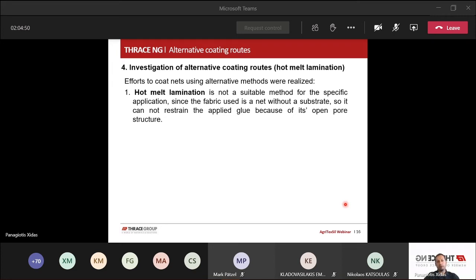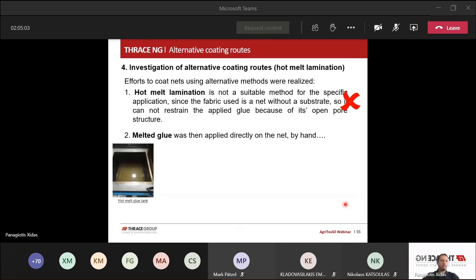So since the use of the lamination machine was not feasible, we tried to apply the glue by hand, very simply, with the aid of a brush. Here in the image, you can see the tank of the hot melt glue. The glue is here at the temperature of 160 degrees Celsius, which is above the melting point of the polyethylene, which was used for the production of the net.